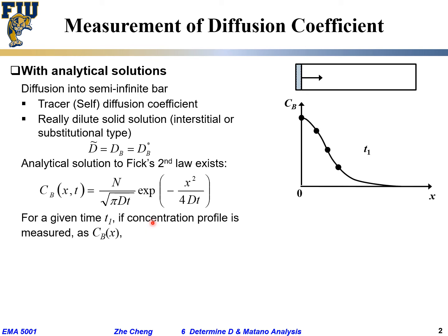Or even if it's not a radioactive tracer, let's say interstitial, you may be using XPS depth profiling, Auger electron depth profiling, or SIMS depth profiling, quantitative. You have some information like this: the change of concentration with respect to location, detected across the depth. You get a certain curve that looks like this.